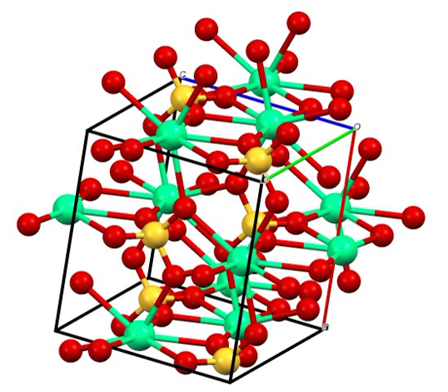Temperatures as high as 170 degrees Celsius are used in industrial calcination, but at these temperatures gamma anhydrite begins to form. The heat energy delivered to the gypsum at this time, the heat of dehydration, tends to go into driving off water, as water vapor, rather than increasing the temperature of the mineral, which rises slowly until the water is gone, then increases more rapidly. The equation for the partial dehydration is CaSO4·2H2O → CaSO4·0.5H2O + 1.5H2O.